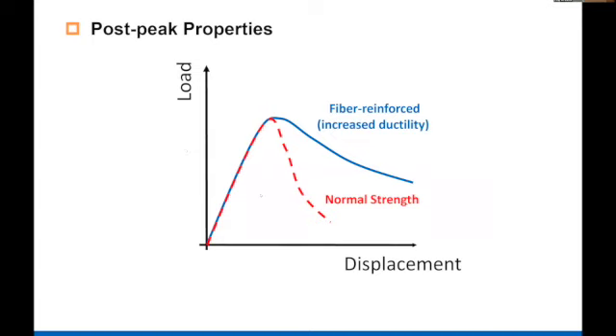So if you look at this response of what we use currently, called fiber reinforced concrete, we are talking about 1% by volume. Fibers could be steel, glass, or synthetic. There is no change in modulus, really not any improvement in tensile strength, but substantial improvement in post-peak. So we call this fracture toughness. And this is, of course, very important in crack control.